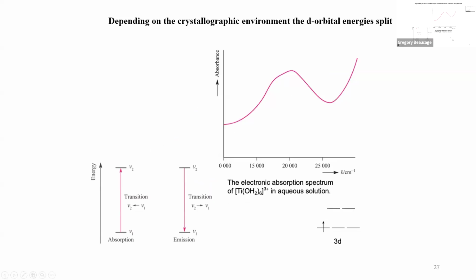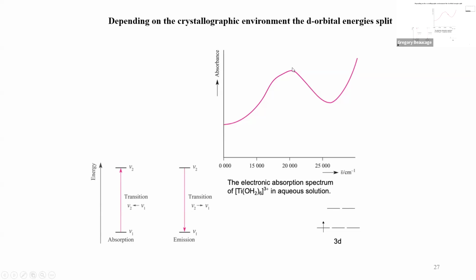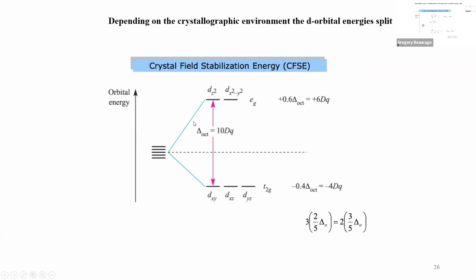Anyway, this is just showing that you can get an absorption band. So you're doing spectroscopy. This could be Raman or IR spectroscopy, and you see an absorption band associated with this transition. Or I guess this is visible UV-vis, right? Probably. And then you see this transition, so you can measure that number. You can put your material in the UV-vis spectrometer, get this peak, and that peak position is a frequency, you can convert that h nu to an energy. So you can actually measure that energy.